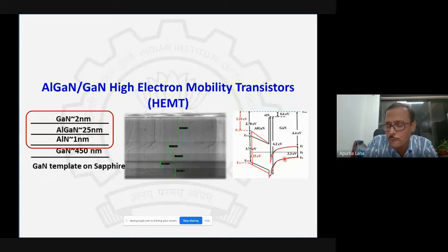If you look at the band structures, because these are polar materials, the structure is polar. So if you mix them, there is a gradient of electric field at the interface. This gradient of electric field will bring charges to the interface, and these charges will be confined in a triangular potential well. This is what we call the two-dimensional electron gas. You don't find any other material that has such properties, right? So you don't have to dope it.